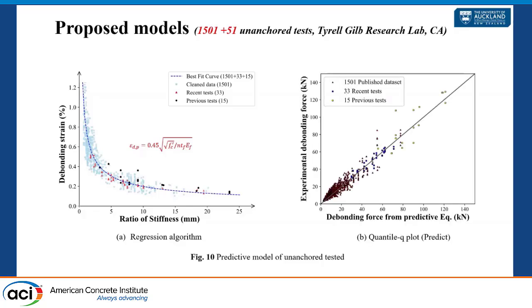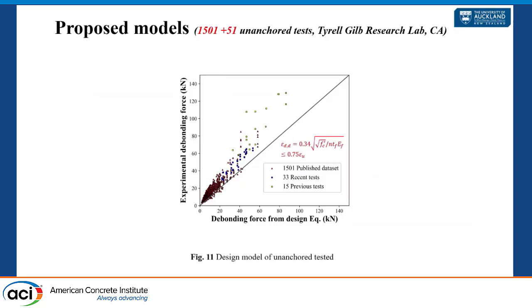We also did a verification of the data. We compared the actual data with our calculated predictive data, and it shows relatively good correlation here. Then, based on our predicted data, we also want to propose another model for design for industry. So we used iterative calculation to make over 95% of the data lie above the 1-1 line, and maintain those data in a safe and reliable range. Then we propose our second model here. It's for design.